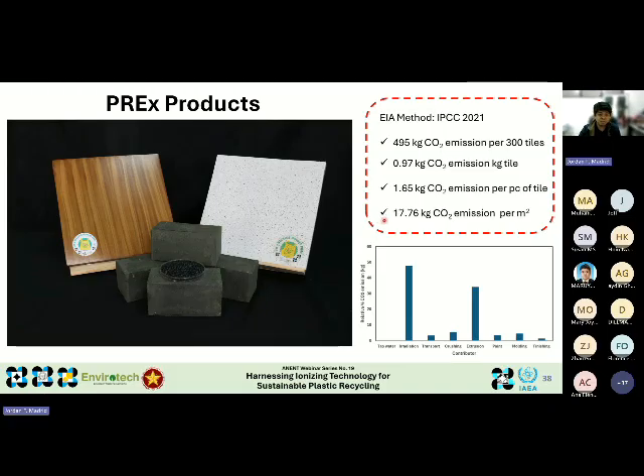What is perhaps more insightful is the breakdown of these emissions. When we look at the relative contribution of these steps, it is clear that the majority of the carbon footprint comes from the electron beam irradiation and the extrusion stages. In the Philippines, we are using a lot of coal plants, and that is used to power, for example, the electron beam facility, so it contributes a lot of carbon emissions. This is an important finding because it tells us exactly where improvements can be targeted.